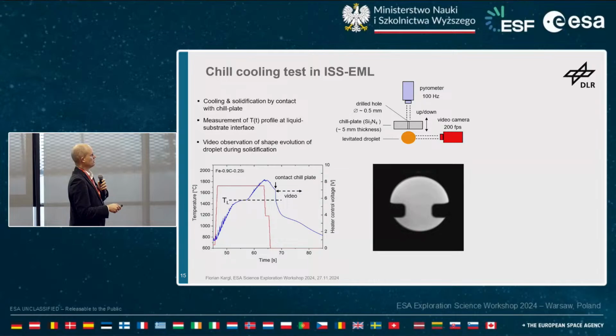So this can be moved up and down, so you contact it. Temperature is still measured when the chill plate is in contact with the sample through a borehole in the chill plate, a very tiny hole. And the sample itself is monitored with a video camera from the side. And we will have a look.